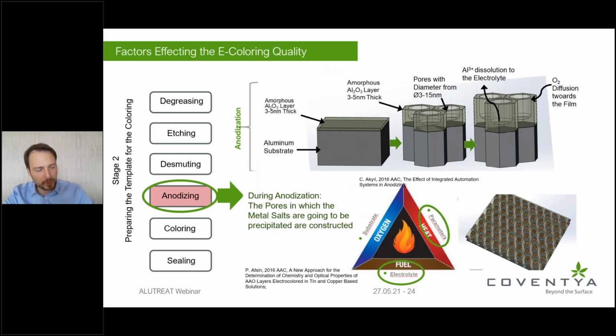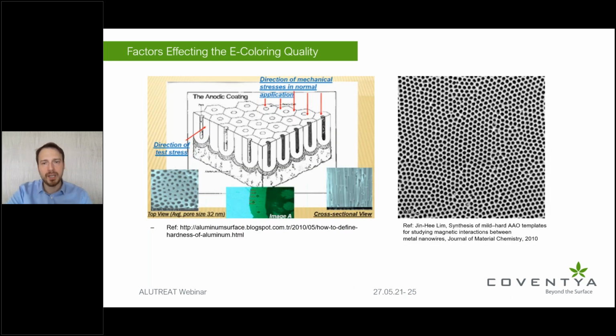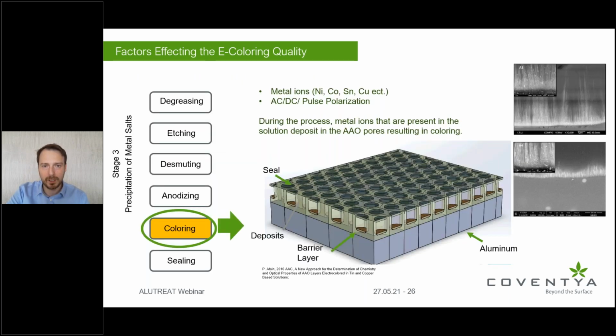When we also look more closely, why anodizing, for instance, is very important for coloring is that, as we said, we are going to be using this as a template. And in reality, it is very important to have these pores structured or distributed throughout the surface, like with these honeycomb-like structures. Then we have the right template, which means the right structure, where by using pulse or AC or even AC-DC type of current, we can start precipitating the right metal salt with the right amount in those pores that will give us the right color, as you can see here.